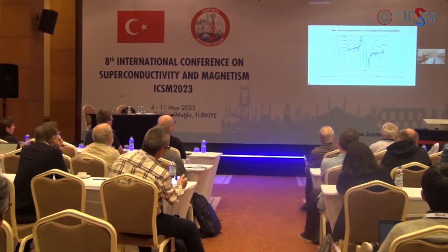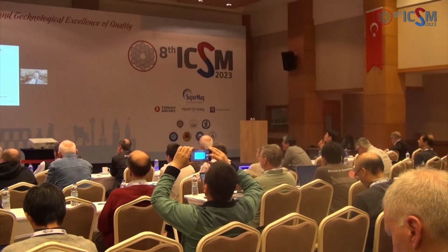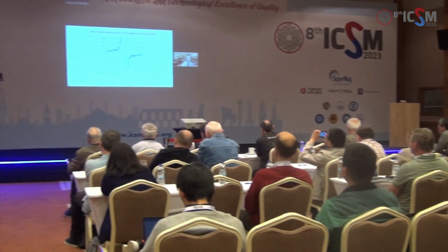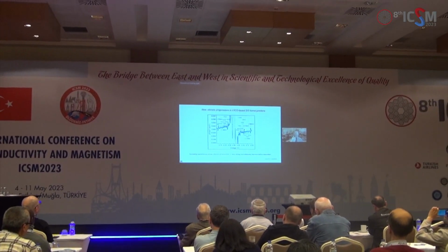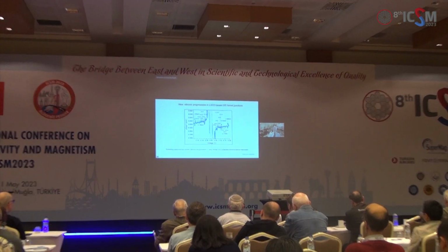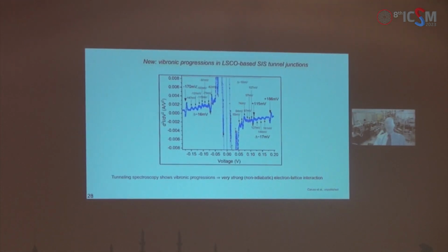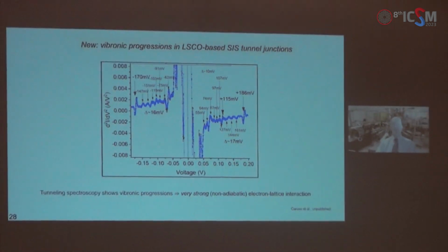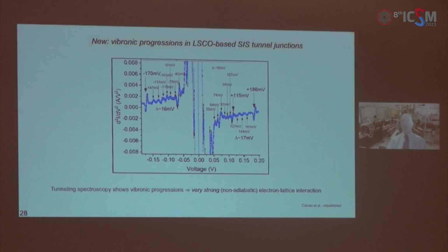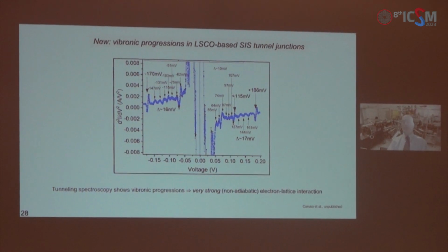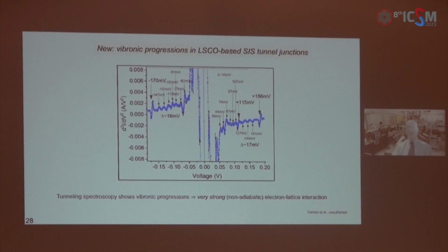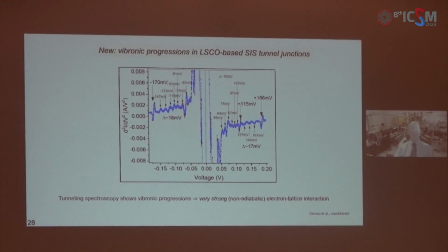Now, what I wish to show here is a new experiment which is even more spectacular. Again, this is spectroscopy of SIS junctions with lanthanum strontium cuprate electrodes. The area of the barrier is something like 1,000 microns squared. But you see very sharp features in the IV, dI/dV, and the second derivative. The second derivative here is measured directly, but we also measure the first derivative, and then we can do the second derivative numerically, and they all agree.